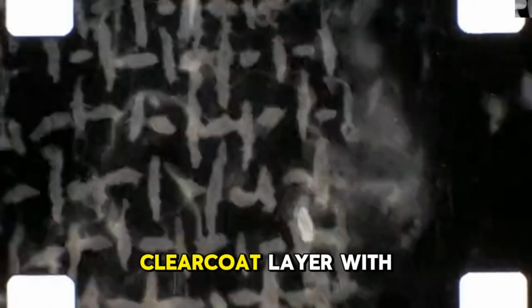The scanning electron microscopy images included in the published study provided the visual evidence that the numerical data implied. Cross-sections of the weathered, untreated control panels showed the fracture network in the clear coat layer with clarity. Irregular channels running through the polymer matrix, their walls rough and chemically altered by oxidation, their openings at the surface visible as the microscopic roughness that scattered light and produced the characteristic dull appearance.